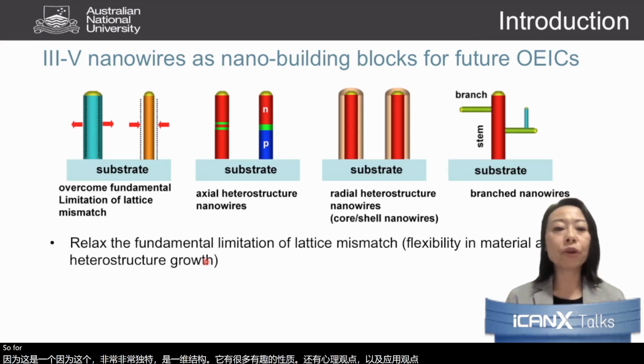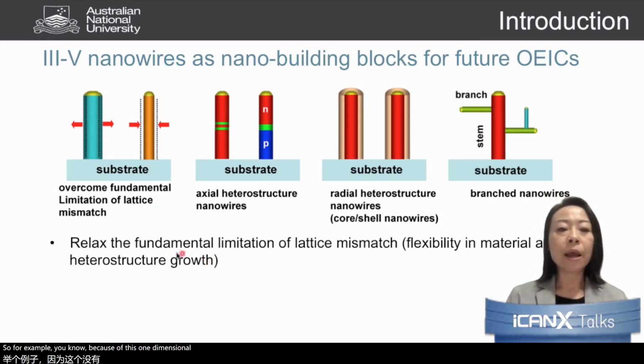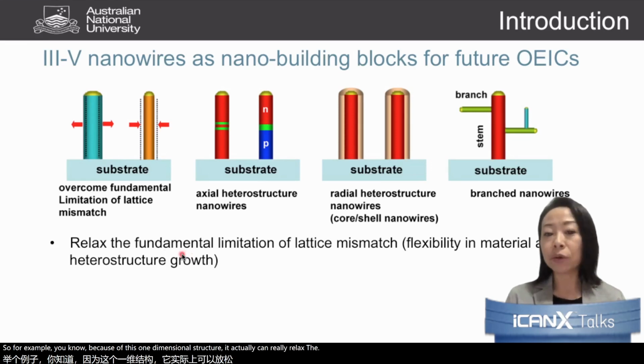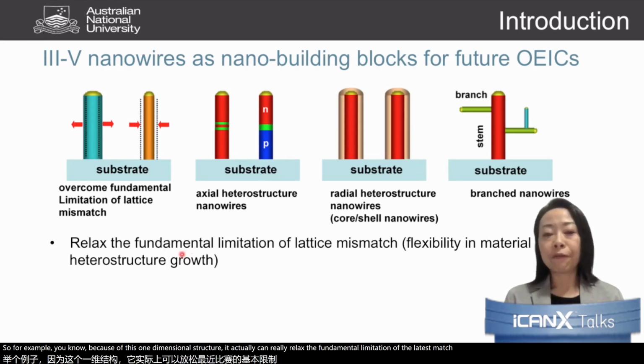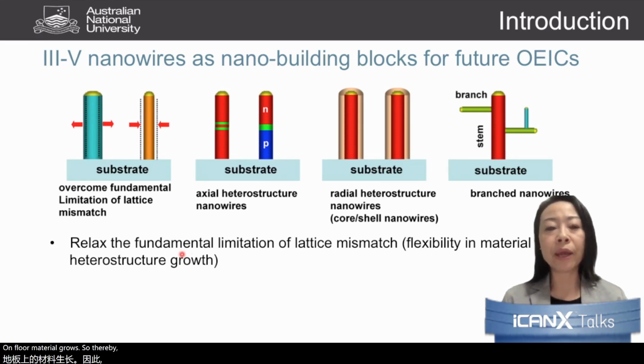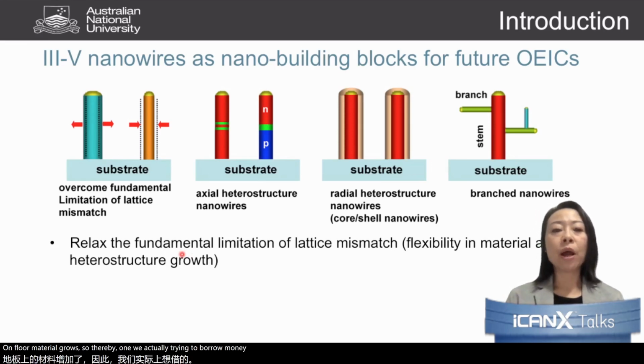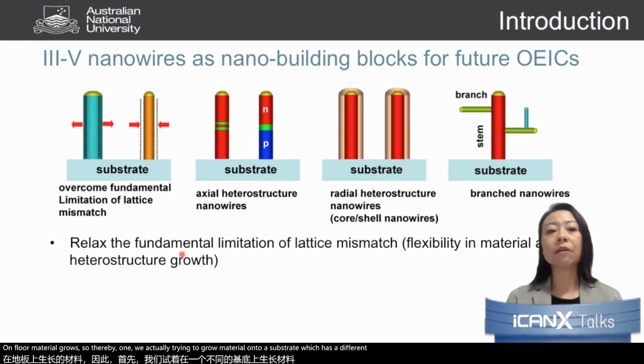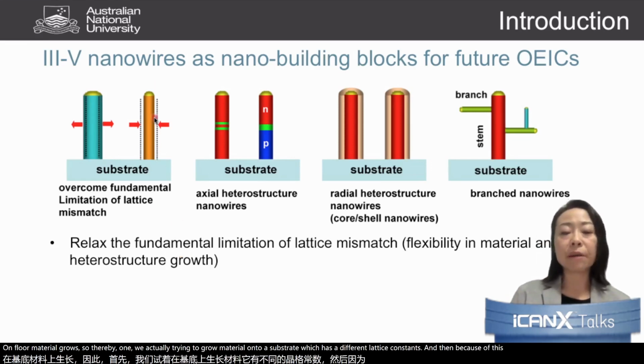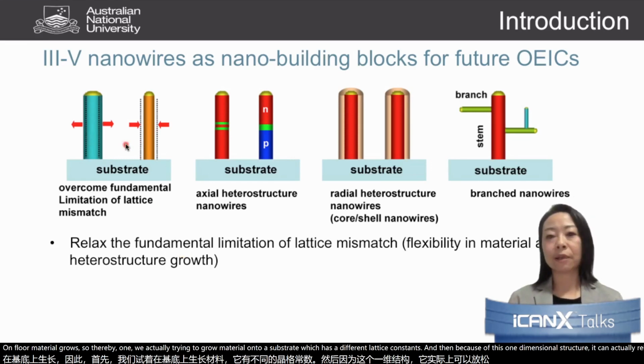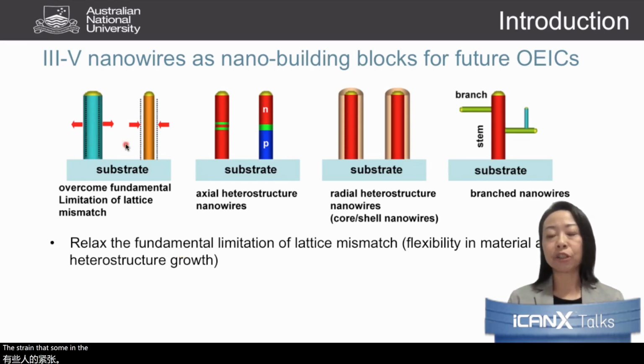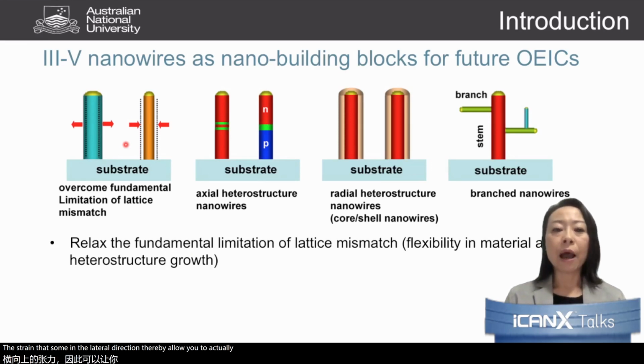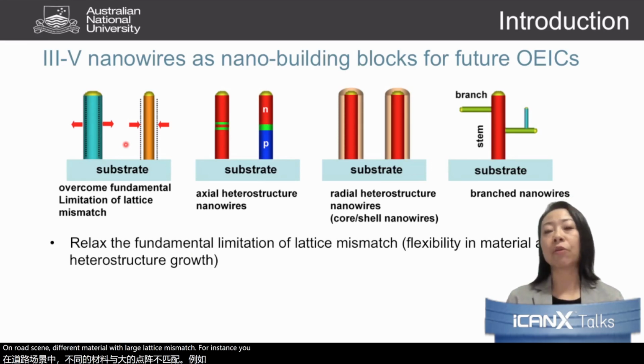So for example, because of this one-dimensional structure, it can really relax the fundamental limitation of lattice mismatch for material growth. So when we are trying to grow material onto a substrate which has a different lattice constant, because of this one-dimensional structure, it can relax the strain in the lateral direction, thereby allowing you to grow different materials with large lattice mismatch. For instance, if you want to grow III-V on silicon, nanowires make it much easier compared to planar structures.